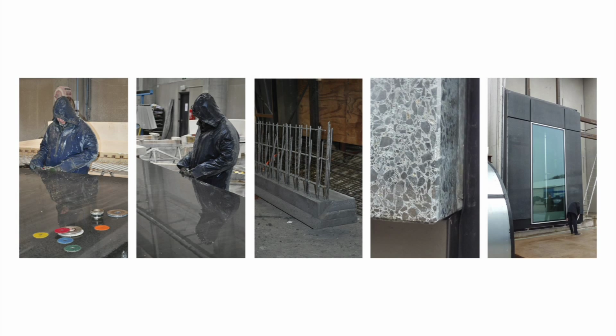As the building evolved, we began to see that this negative mould that we'd made in the formwork was turning into positive elements, which were creating the overall space. We really enjoyed a lot of the way that these junctions between columns and surfaces came about. Here, for example, we tried to articulate the actual movement of the staircase with the way that it was structurally supported, so there's a distinction between the column and the wall surface. We also wanted to avoid kicker joints between the staircase and the walls, so we cast the walls first. That's where you get this detail line running underneath the soffit of the upper flights, and how we've managed to achieve a very monolithic feel to the stair as you're looking down onto it.